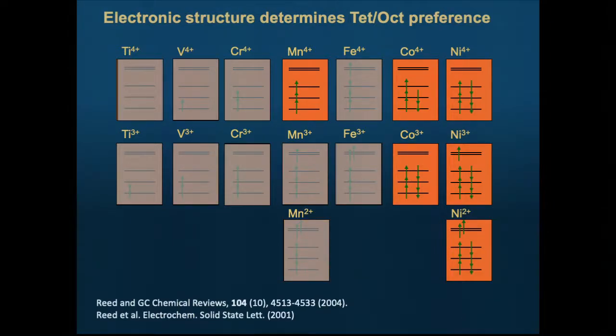So those are out, but the one you can use is manganese 4. This is perfect. 3 electrons, if you don't oxidize it, you stabilize octahedral coordination. And now you see where our battery chemistry comes from. We use manganese 4, we use cobalt 3. This is the perfect ion. You have 6 electrons, non-spin polarized. You have 6 electrons that fully favor octahedral coordination. And indeed, the one element that we never ever see move around is cobalt 3.